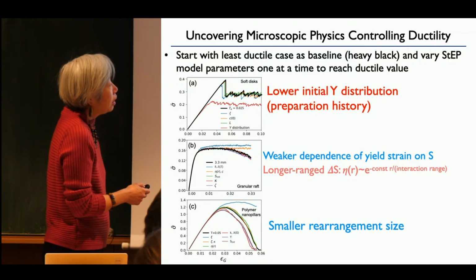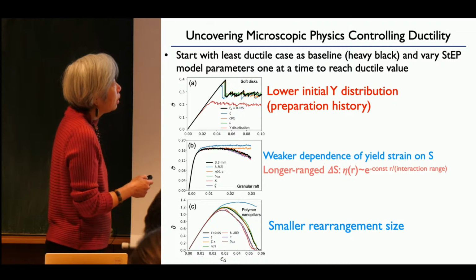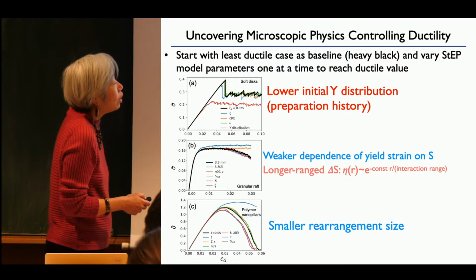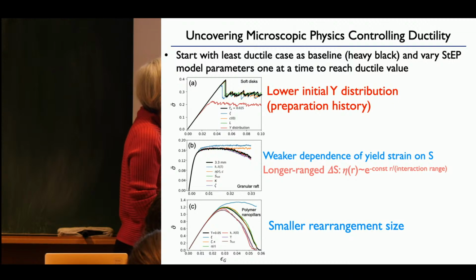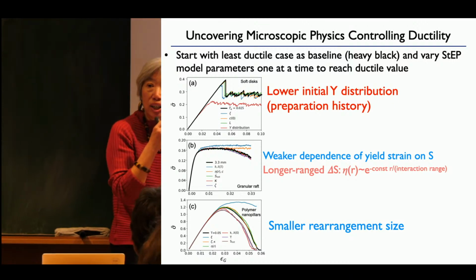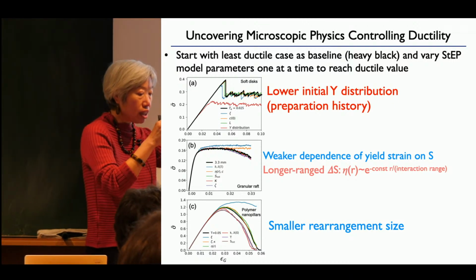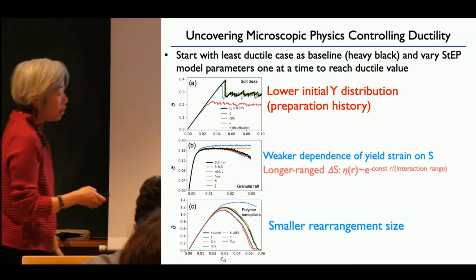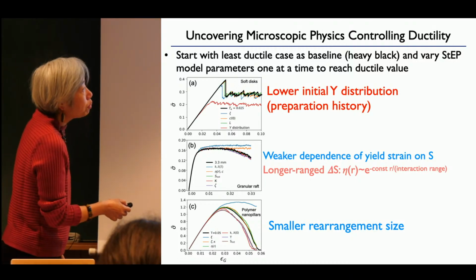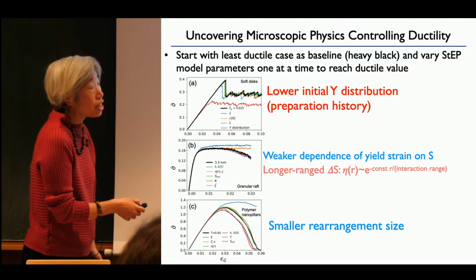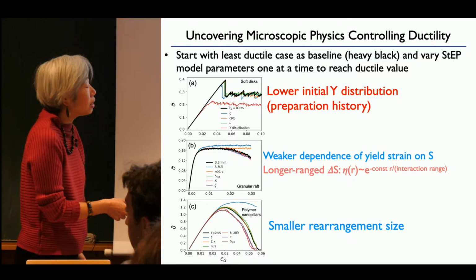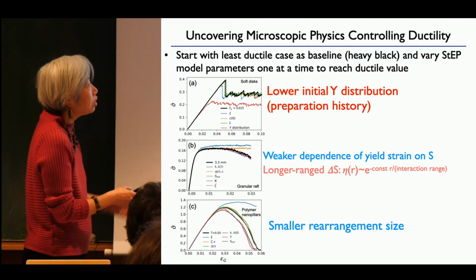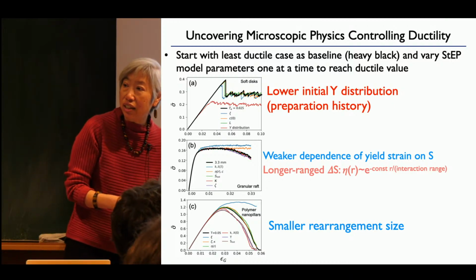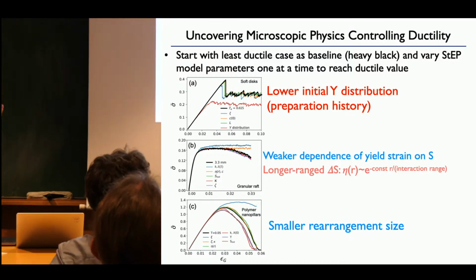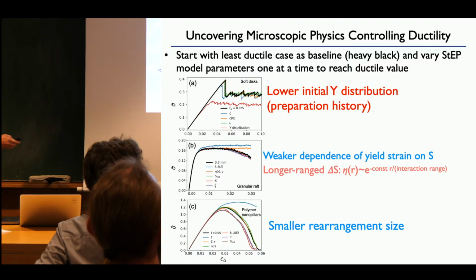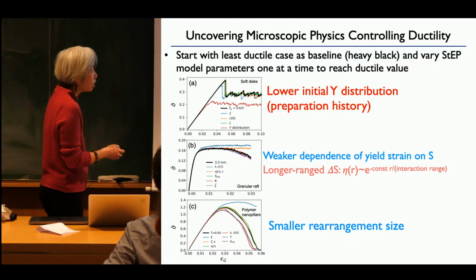And the second thing is that in the more ductile case, well, in both cases, what we find is that this decay of the short-ranged effect, how the short-range softness changes when you have a rearrangement, decays with the distance divided by the interaction range. And that is what's changing in the two systems. And so in the more ductile, the short-range facilitation effect is shorter range. Okay, the near field effect is shorter range.